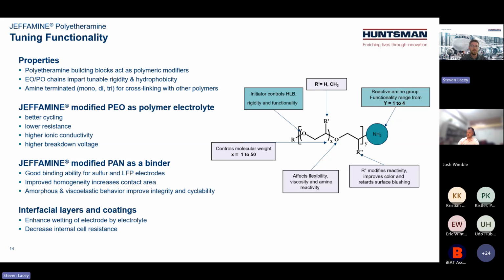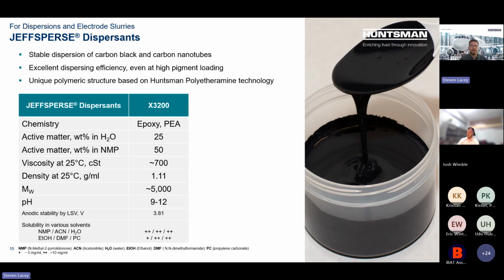And as I said, also for coatings and wettability, the hydrophilicity and the tunability of these with the different functional groups and also the reactive amine groups, you can very easily functionalize and alter the chemistry and also alter the properties. So there's a lot of potential here for a lot of different things. And from a dispersant standpoint, this is actually very efficient for carbon black, a lot of different carbon blacks on the market and different carbon nanotubes, not only the one that we produce. So also for pigments and in the coatings industry, it's very important. And from a battery perspective, we also can use this particular dispersant, X3200, in both water and NMP systems to enable dispersion and very good stability in solution.